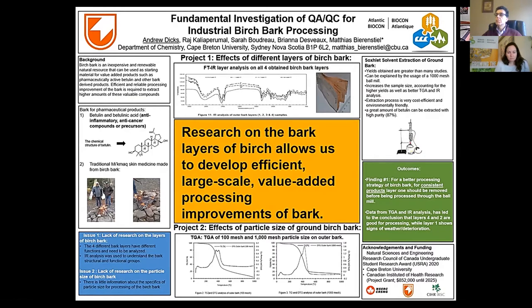And the outcome of our study is that for a better processing strategy of the birch bark for consistent products, layer one should be removed before being processed through the ball mill. As well, data from TGA and IR analysis has led to the conclusion that layers four and two are very good for processing, while layer one shows signs of weathering deterioration and before being processed and extracted should be taken out.